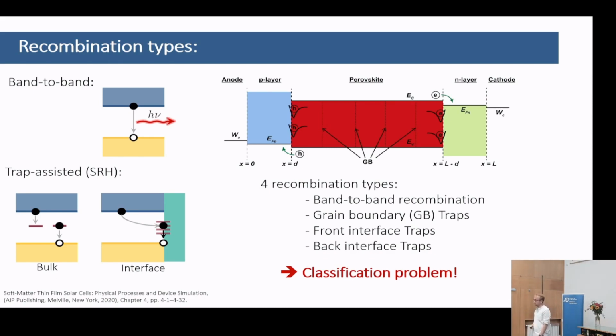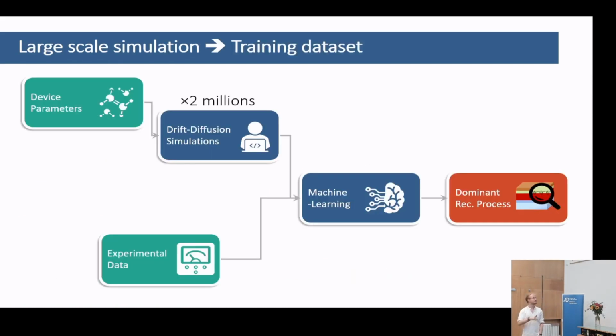And so to do that classification, basically our workflow was, we started with a very wide range of parameters that are still meaningful. We ran millions of simulations of light intensity dependent JV, and then we trained a machine learning model to be able to classify and recognize which type of data means which type of recombination. And then once that machine learning is trained, you can actually feed it experimental data, and it's going to do the same job. It's going to tell you, well, this is my limitation.